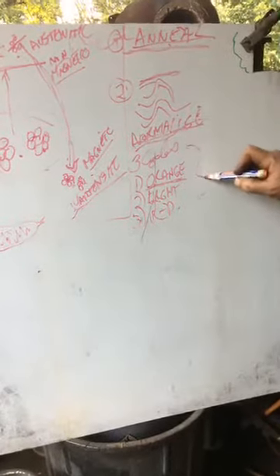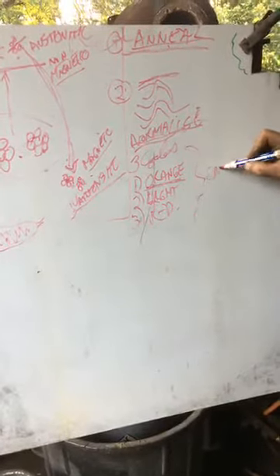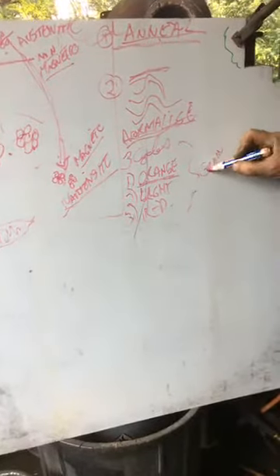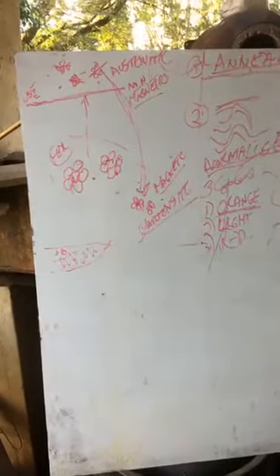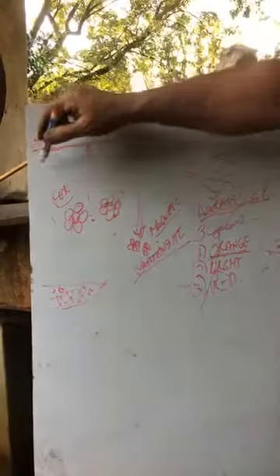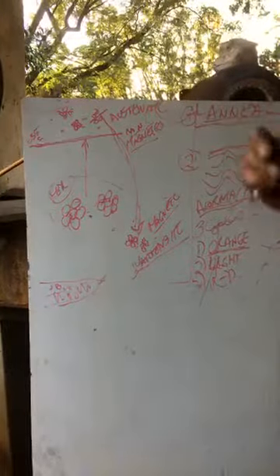And that's all done to manage the grain structure of the steel and to de-stress it. So you're managing the grain structure. I've run out of board here, but if you heat it up higher, it starts reverting back to a larger grain structure again. So there's a narrow band over here that you're working in. So you can't let it soak for too long, and that's why gas forge is really handy, because gas, you run it at an even temperature and it's easy to keep it in that zone.